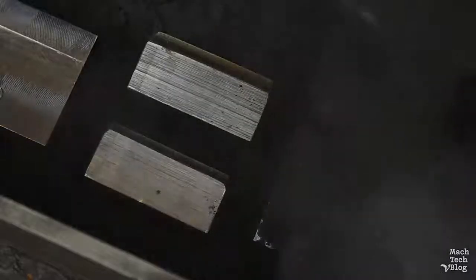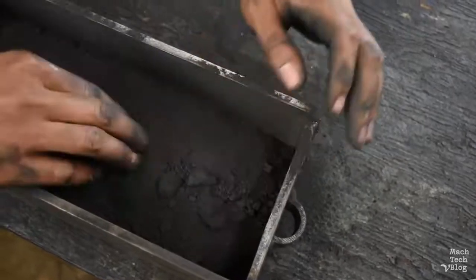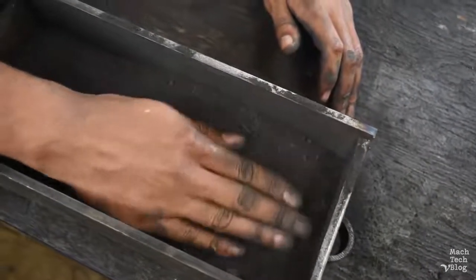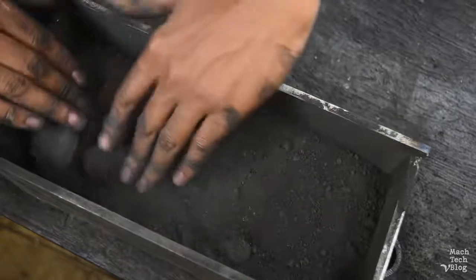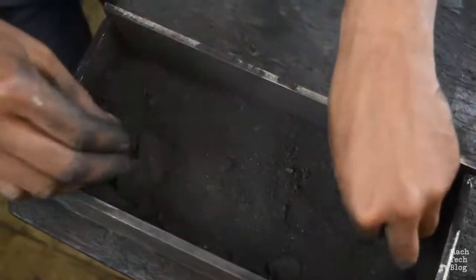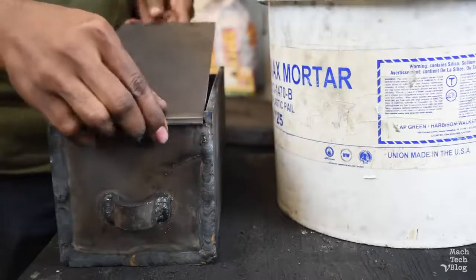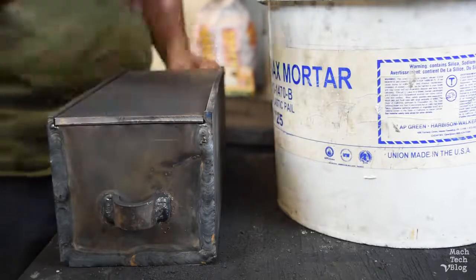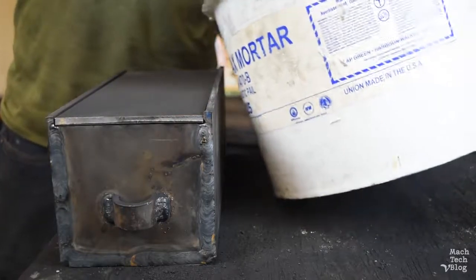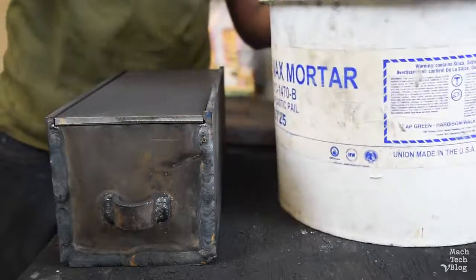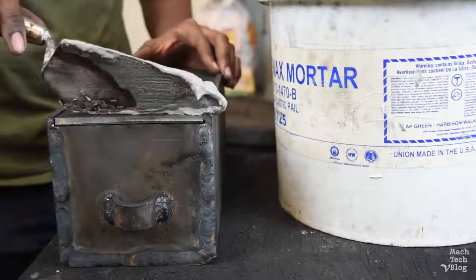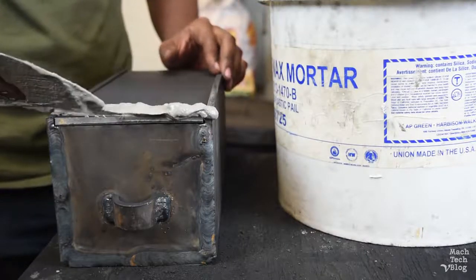Then pour enough carbon on top of the blocks to cover them by at least 1 inch. Put the lid on top of the box and fill in any gaps with fire clay or refractory mortar to form an airtight seal. The mortar should ideally be a little thicker than this.